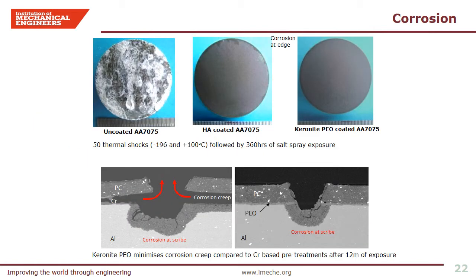This slide shows the effect of coatings on the corrosion resistance of the aluminum alloy. The top row shows the hard anodised layer already offers improved corrosion resistance to the aluminum alloy, but still shows issues at corners via truncated V-cracks that are often responsible for fatigue and corrosion fatigue reductions. On the other hand, the PEO coating shows no sign of such corrosion issues due to its ability to offer uniform coating coverage even on the sharpest edges. The bottom left image shows how upon scratching the polymer layer, corrosion migrates under the powder coating, resulting in corrosion creep, peeling and blistering. On the bottom right, a thin PEO interlayer not only improves the powder coating's resistance to scratch, but also prevents corrosion creep and subsequent under-film corrosion migration.